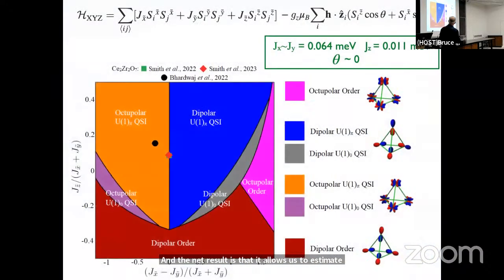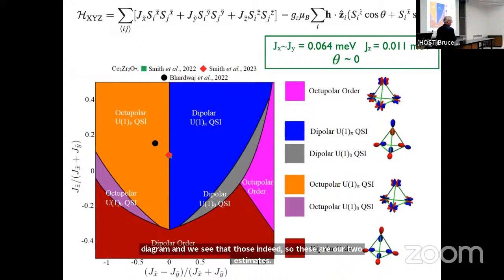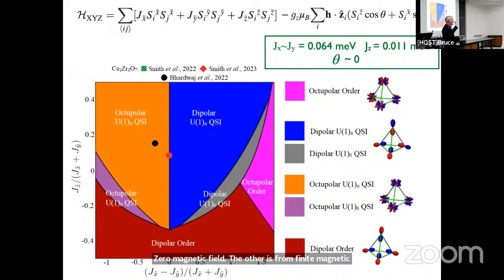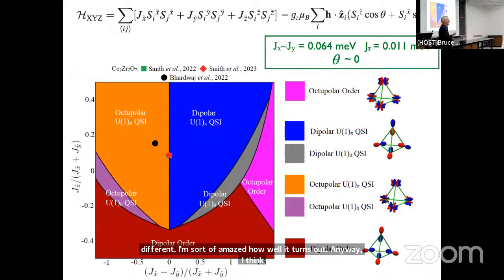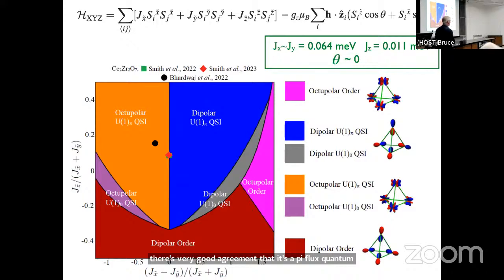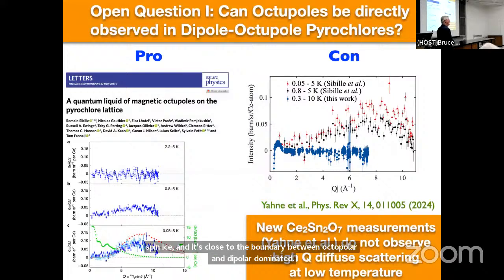And so if we have that, we can put those on our phase diagram. And we see that those indeed, so these are our 2 estimates. One estimate is from zero magnetic field. The other is from finite magnetic field. This is a competing group working completely independently from us on different crystals. Everything's different. I'm sort of amazed how well it turns out. Anyway, I think there's very good agreement that it's a pi flux quantum spin ice, and it's close to the boundary between octupolar and dipolar dominated. Okay, and that's pretty much all I want to tell you about.